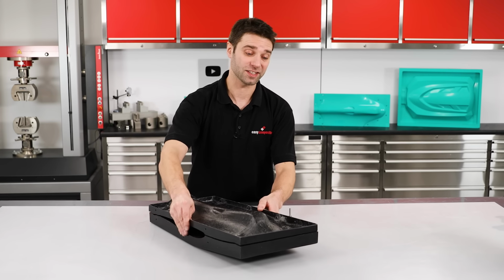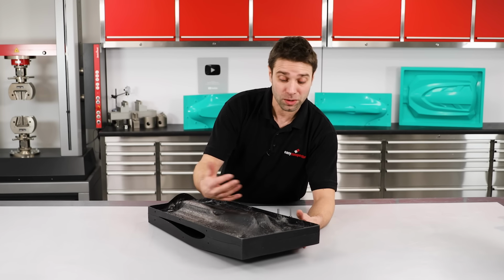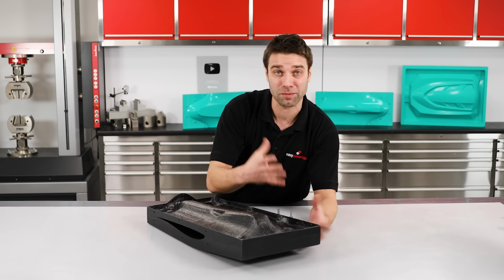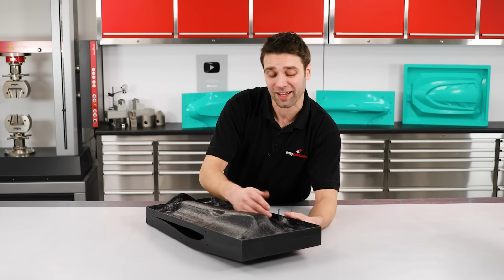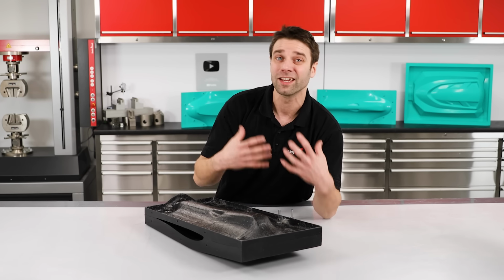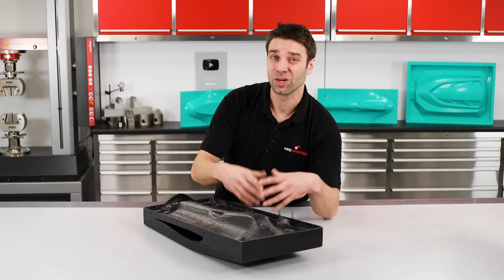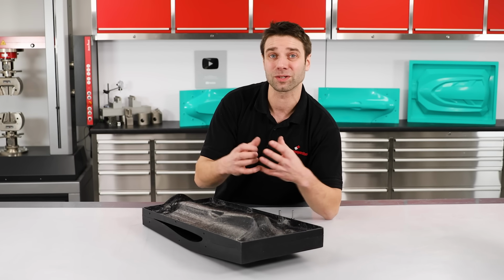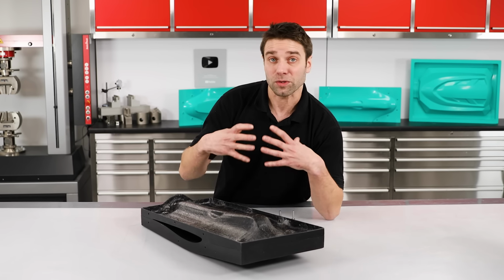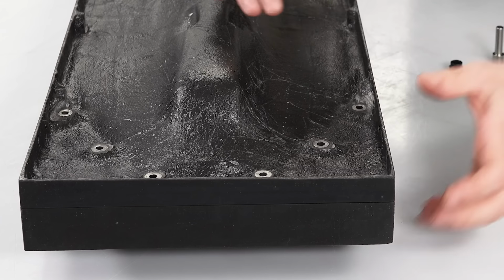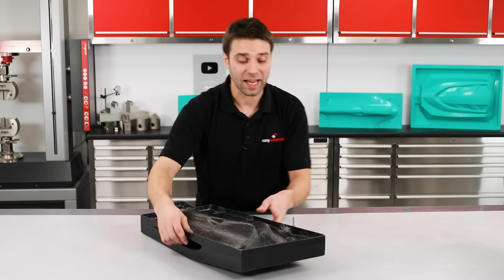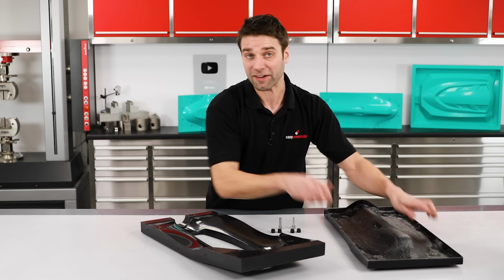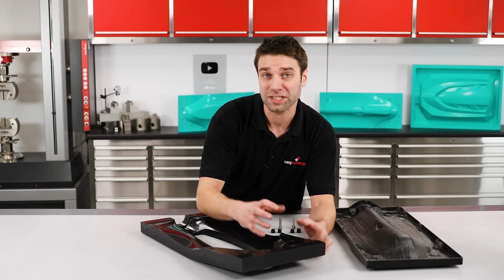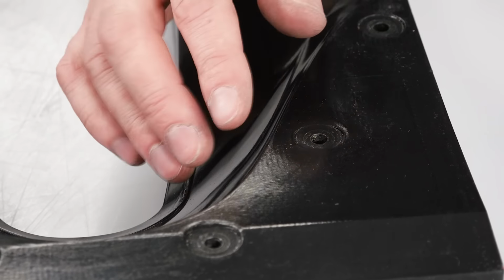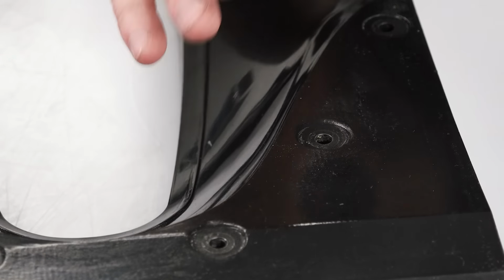The sections of a split mold need to be accurately aligned and securely clamped together. You could simply drill a hole through the flanges here and put a bolt through that, but if you were to do that, those holes are going to wear quite quickly and you'll soon have alignment issues. Also, if you over tighten the bolts, you can cause damage to your molds. So to overcome these problems, these molds feature split mold clamping bushes. Now, they're a little bit difficult to see buried inside the laminate here, but these bushes completely take care of your alignment and prevent any wear and damage to your molds.